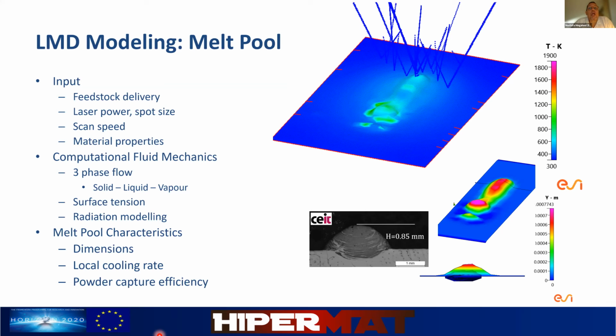What we get out of this model are the melt pool dimensions, local cooling rates, and the powder capture efficiency. So the capture efficiency here in this sense will include how wide is the melt pool and how much of stray particles are still captured by the melt pool. So the result of powder efficiency is not only a nozzle question, but it's also the combination of nozzle, standoff, and melt pool size. On the right-hand side, an animation was running showing you the starting point, which is usually not the final state of the melt pool.